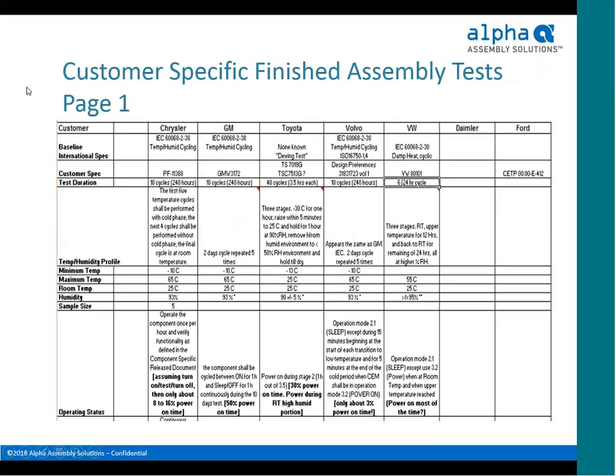All right, and there are also customer-specific tests. You name a customer and they've probably, a big OEM, they've probably got some sort of test in their test scheme somewhere, especially in the automotive side. Or any high reliability programs will tend to have tests in their qualification scheme specifically designed to test electrochemical reliability of flux. The most important thing about these tests is that they are tested with bias present at elevated temperature and humidity levels, designed to be a catalyst to dendritic growth or to determine if there's any leakage current occurring across non-common conductors due to the presence of a flux residue.